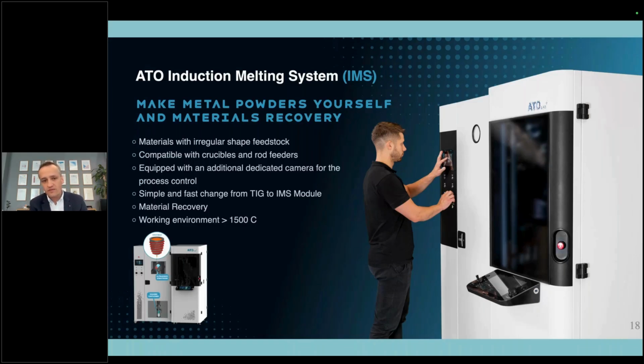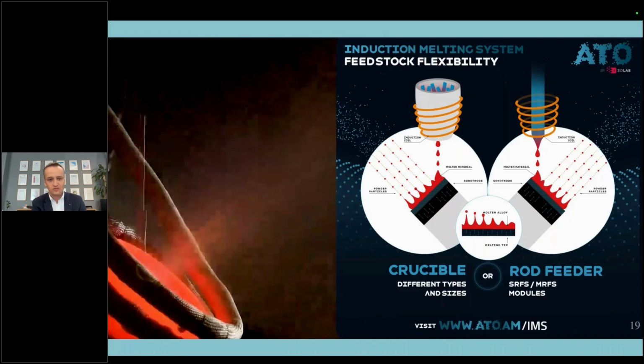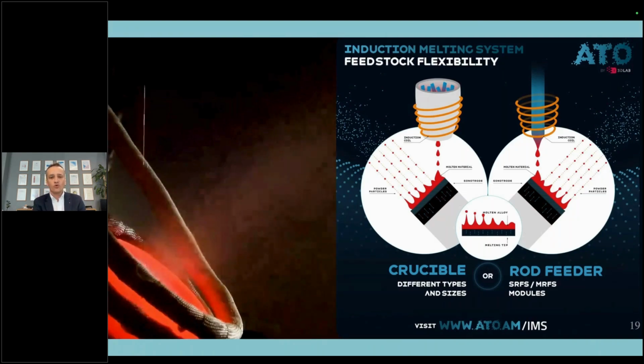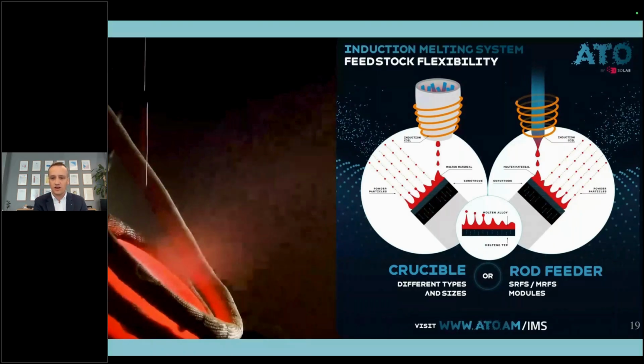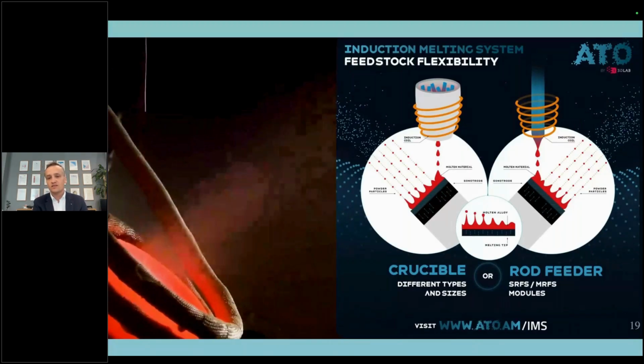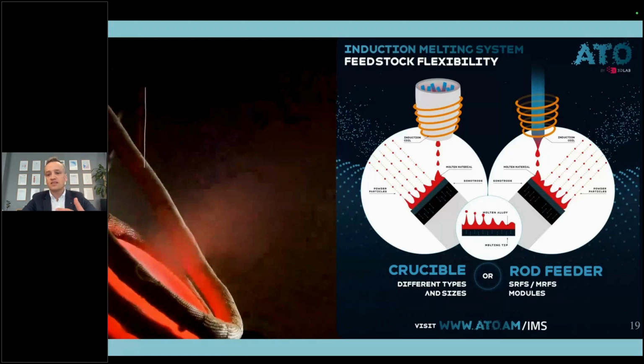I think this graph can also be helpful for you because it's showing that we can work with both crucible and rod feeding systems using our induction melting system. I will explain how it works. Obviously, we can work with different sizes and different types of crucible, depending on the material. But sometimes, if you would like to avoid cross-contamination from the crucible itself, you can feed your induction coil directly with your rod. That's how we achieved, for example, great results with magnesium.